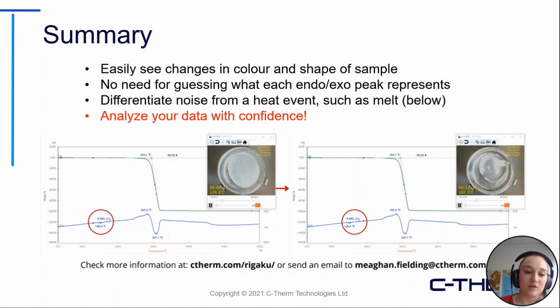You can differentiate noise from the heat event, such as a melt below. So in this sample, which was the PHBH straw we looked at earlier, the melt event, which is circled in red there, does not look like a melt event. It just looks like noise. So if you were to analyze this, a large percentage of people, I'm sure, would miss this. And with sample observation, you can't miss it. So you can analyze your data with confidence, really, and just eliminate the guesswork.